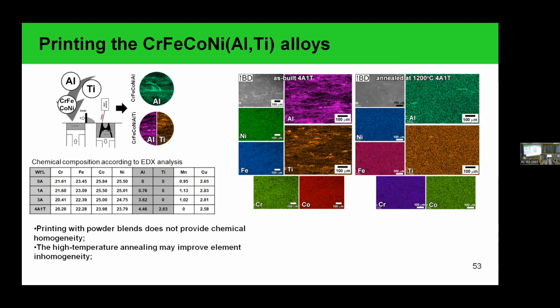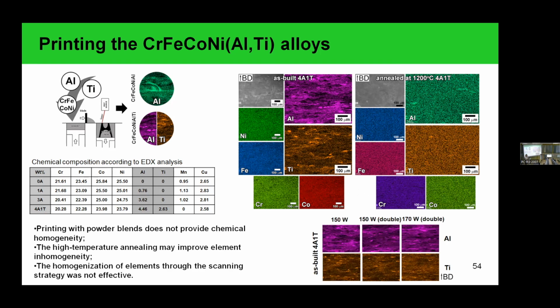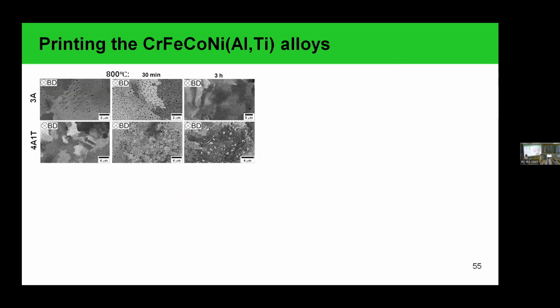And again, the annealing at high temperature can be suitable to improve this chemical homogeneity of our materials. But the scanning process, like higher laser power or double scanning, doesn't provide the appropriate results. There is still an inhomogeneous element distribution in our material.